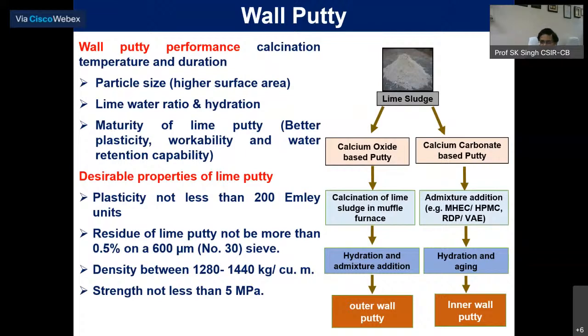One thing we have carried out is taking lime sludge, calcining it and making calcium oxide, adding cellulosic polymers and other things, and with all those additions we make outer wall putty. Similarly, with a calcium carbonate and white cement based system, we add about 77 to 80% lime sludge, white cement about 15 to 17.5%, and some additives. So it is very cheap. Our cost will be only 55 to 60%, so it is a low cost material, since those industries will be in nearby places. So that we have carried out.